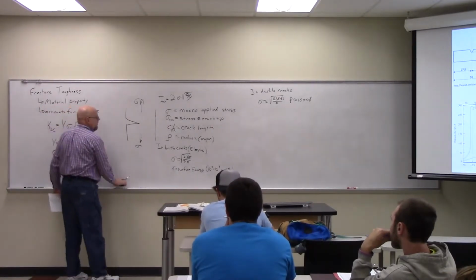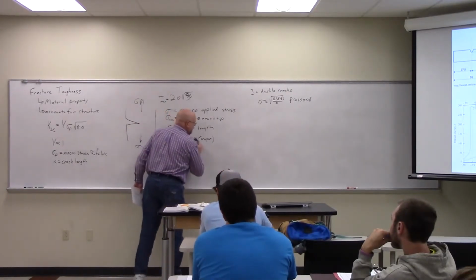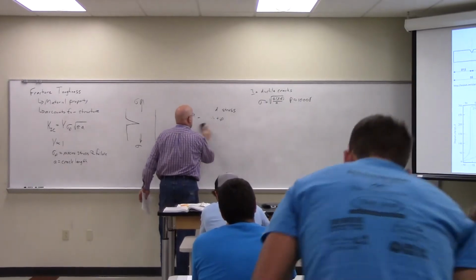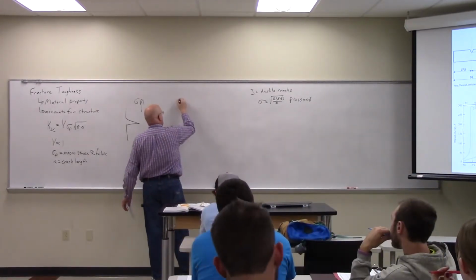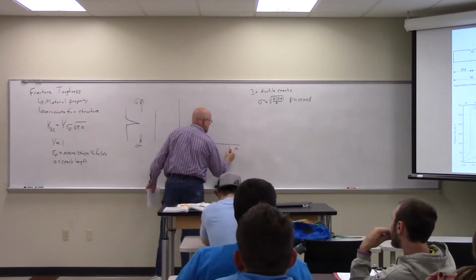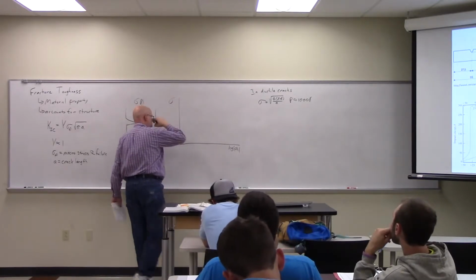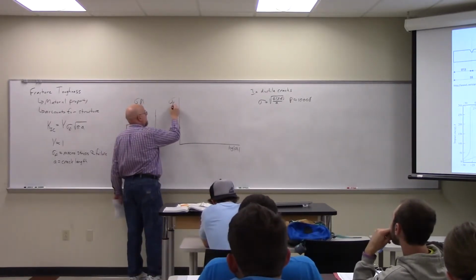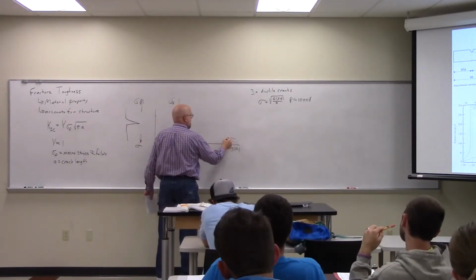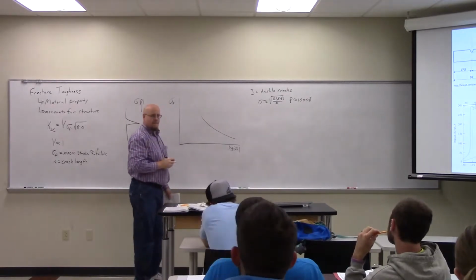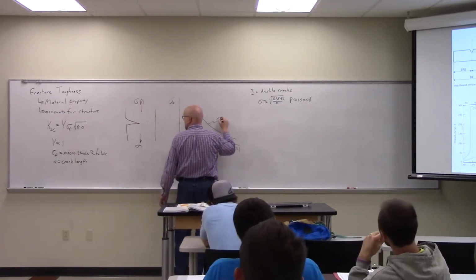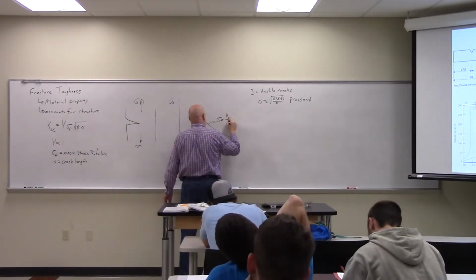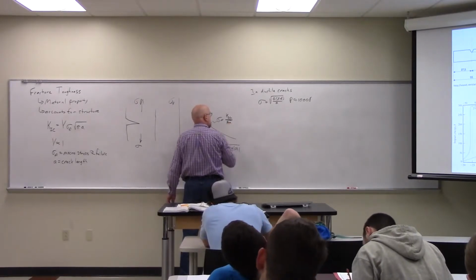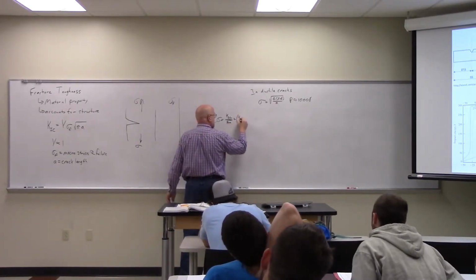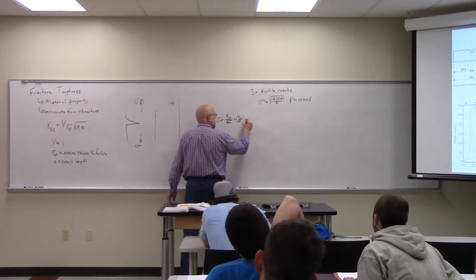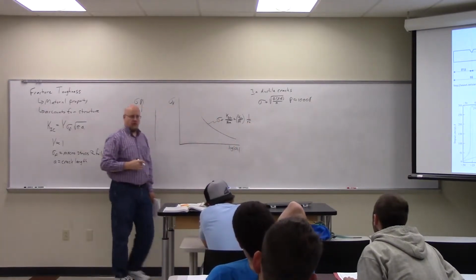That means if I were to plot the stress at which something fails, actually it's usually plotted on a log plot, and I plot the failure stress, it will follow this kind of behavior. This is sigma equals K1C over the square root of pi a. Or, K1C over the square root of pi, which is a constant, times 1 over the square root of a. So essentially it's a 1 over square root of a dependence.